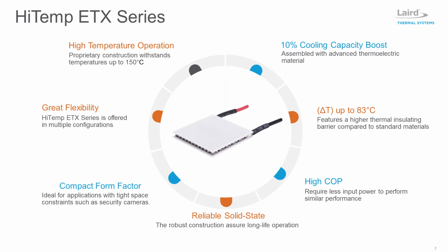Assembled with advanced thermoelectric materials, the HiTemp ETX series boosts cooling capacity by up to 10% compared to standard materials. It also features a higher thermal insulation barrier that delivers improved temperature differential with a delta T max of 83 degrees C. This series also maintains a high coefficient of performance to minimize the amount of input power required to operate and reduces the heat rejection requirement to the hot side, which is critical in poor heat sinking applications such as security cameras. To meet unique application requirements, the HiTemp ETX series is available in multiple configurations, covering a wide range of footprints, cooling capacities, and voltage ranges.